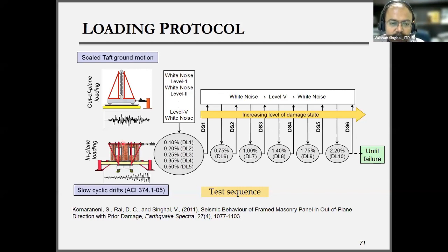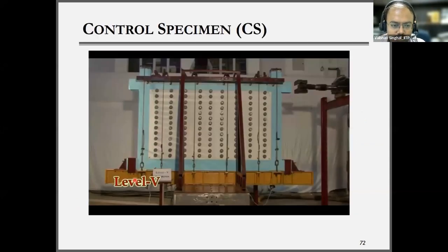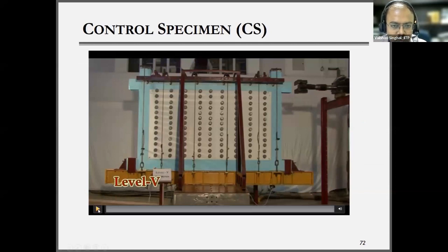And then after that, we recorded all the displacement, accelerations, and other responses. And then we applied some in-plane load, till we observed some cracks, some damage. And then again, we applied the out-of-plane loading and continued the sequence of in-plane load, then again out-of-plane load, till the complete failure. This will be more visible, I think, let me show you this video, then it will be clear.